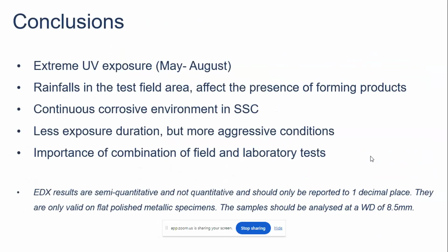Although the exposure was longer for the real marine environment, the continuous corrosive environment in the salt spray chamber played a crucial role in the formation of these products, because the conditions were more aggressive. So in order to have a safe conclusion about the performance of this duplex system, it is very important to have a combination and a comparative study of field and laboratory tests.